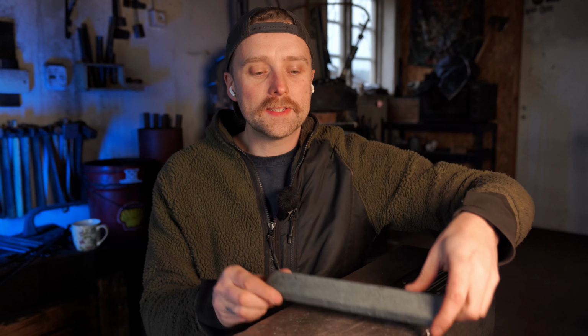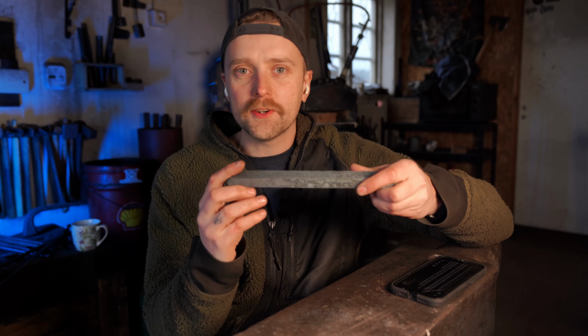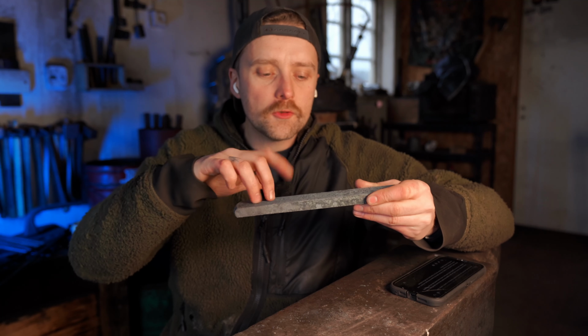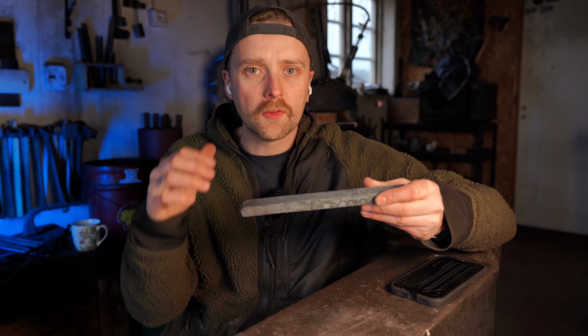So the way that it works is that you can imagine this billet has about 80 layers or so now, and what I'm going to do is drill many tiny holes all over the billet. And when I drill a hole, it creates kind of a valley, exposing those layers all around the hole. And when I then heat it up and flatten those valleys out, the layers will still be exposed, creating that raindrop pattern. That's the idea anyway.